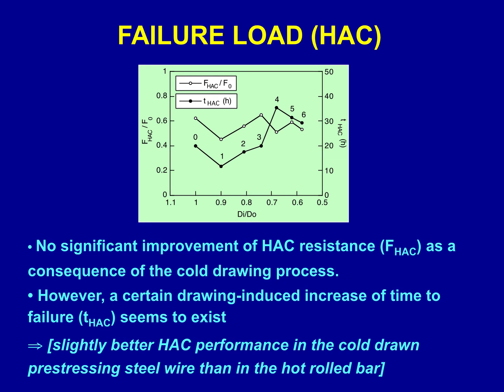However, a certain drawing-induced increase of time to failure, T_HAC (hydrogen-assisted cracking time to failure), seems to exist. The result is a slightly better hydrogen-assisted cracking performance in the cold drawn prestressing steel wire than in the hot rolled bar, with a real increase of time to failure.